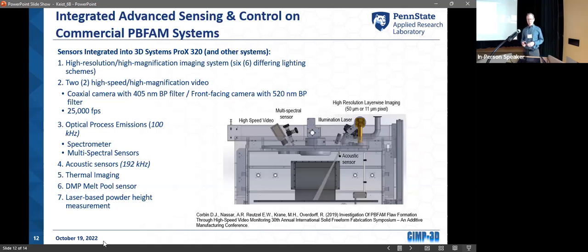We have a large program at CIMP-3D dealing with sensing and trying to do in-situ sensing during the build. And this is an example of a powder bed process, which I told you may take weeks at a time to do your building. We've added things like high resolution cameras, coaxial cameras, high frame rate cameras. We've done things with optical process emissions where you're looking at the spectroscopy coming off the laser interaction with the melt pool. And then we also do things like adding acoustic sensors. In this case, we're looking for the cracking that I showed before, understanding how that cracking occurs and seeing if we need to stop the process with those acoustic sensors. We've done some work also with thermal imaging and melt pool sensors, and also laser profilometry to understand the laser height as well.